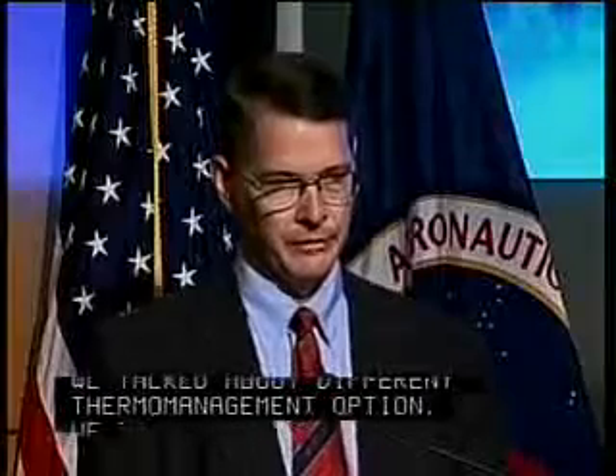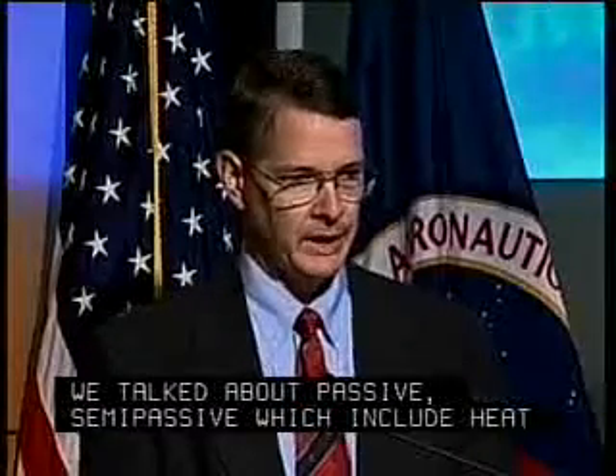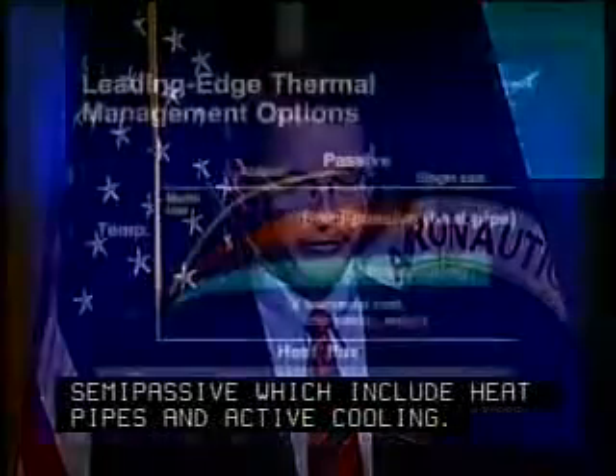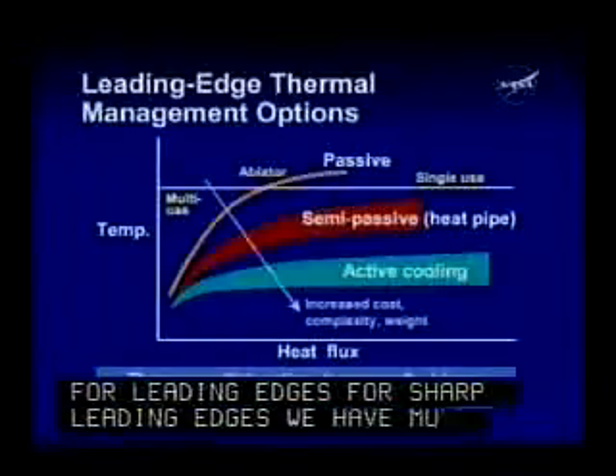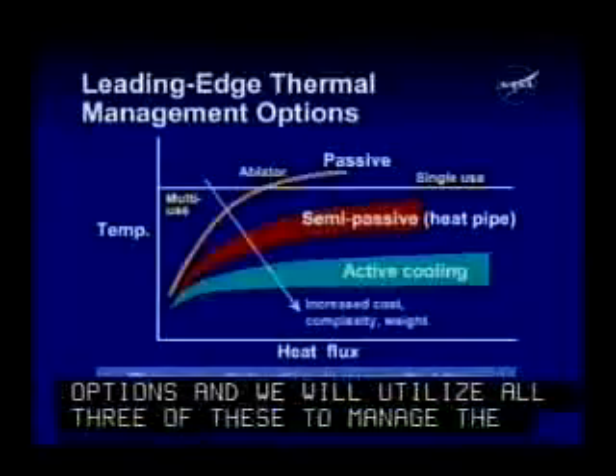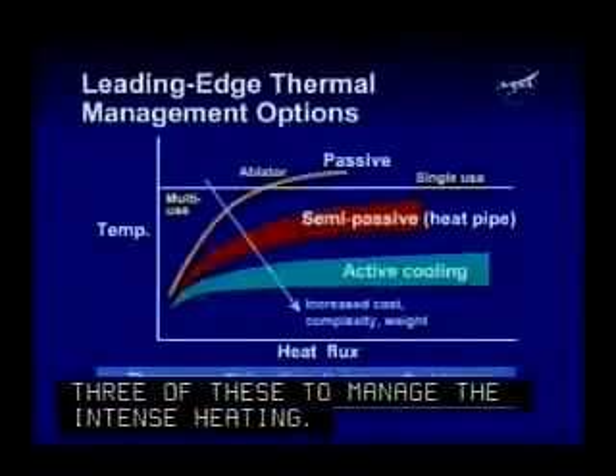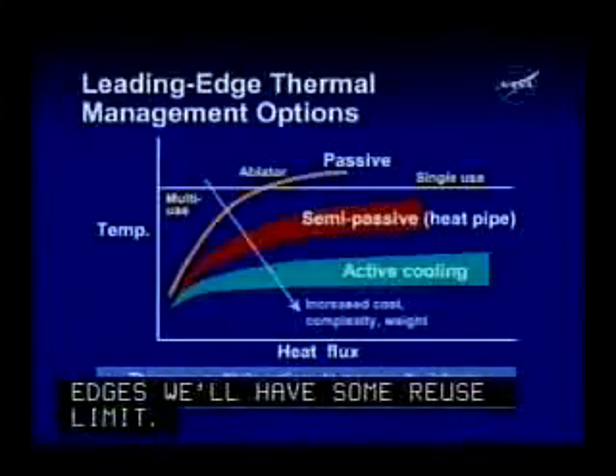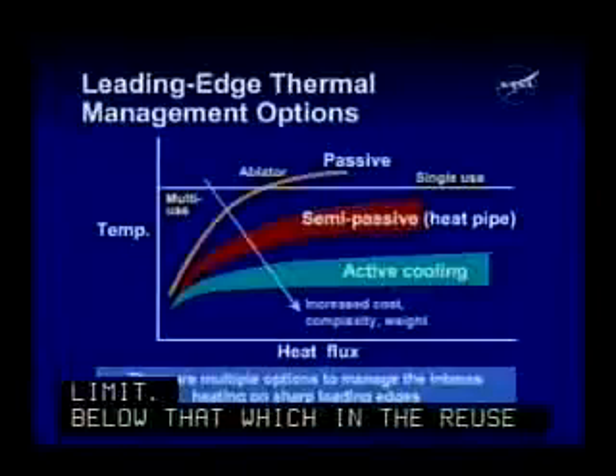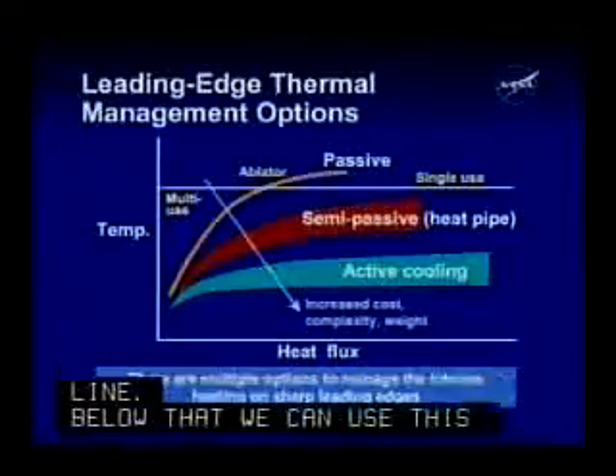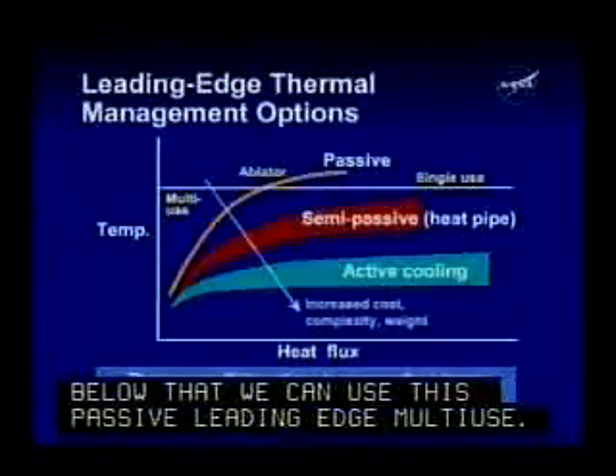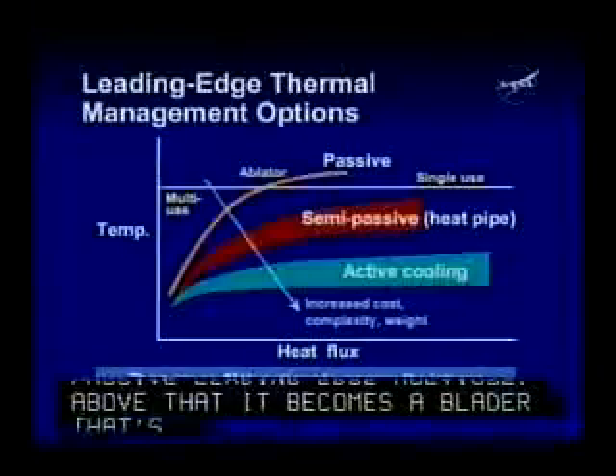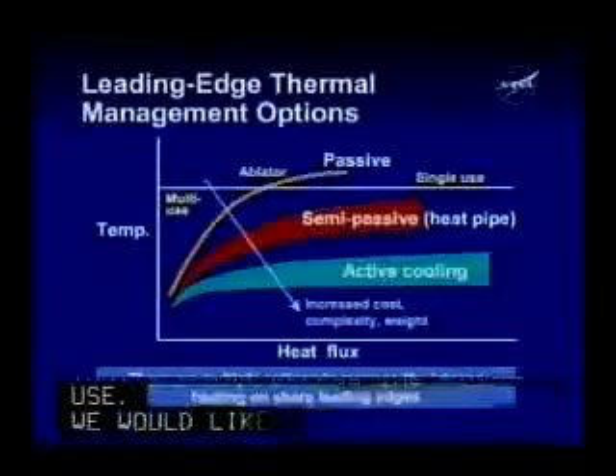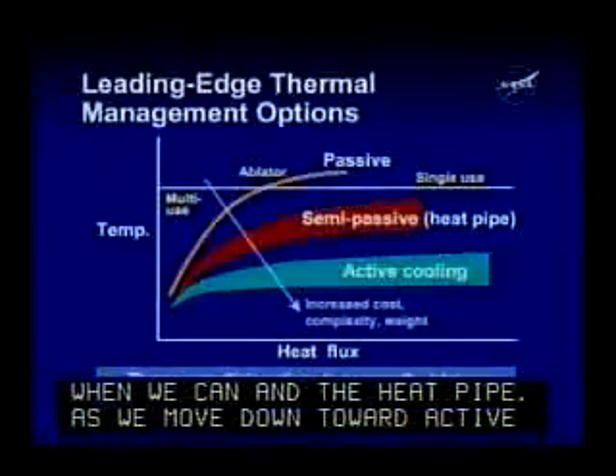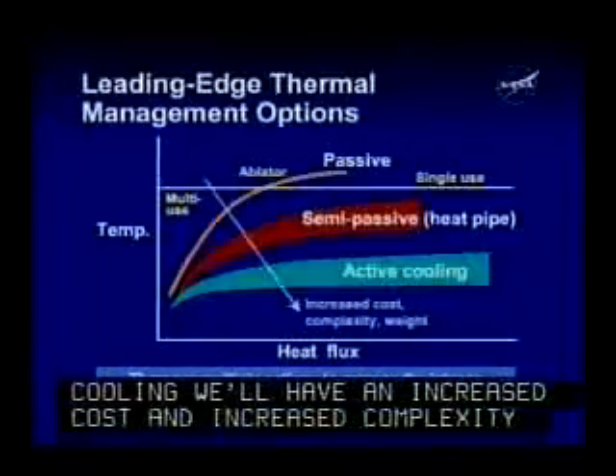Okay, if you remember back a few minutes ago, we talked about different thermal management options. We talked about passive, semi-passive, which included heat pipes, and active cooling. For sharp leading edges, we have multiple options, and we will utilize all three of these to manage the intense heating. If we look first at the passive leading edges, we're going to have some reuse limit. Below that, which in this case is represented by the yellow line, we can use this passive leading edge multi-use. Above that, it becomes an ablator. It's going to recess, be single use. We would like to use passive when we can, then heat pipe, or semi-passive, then active. As we move toward active cooling, we're going to have increased cost, increased complexity, increased weight.